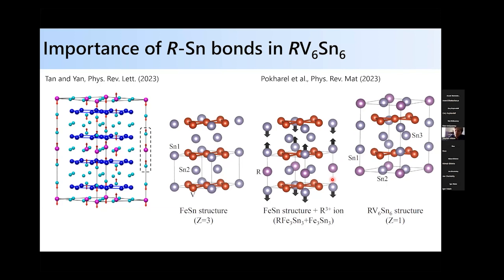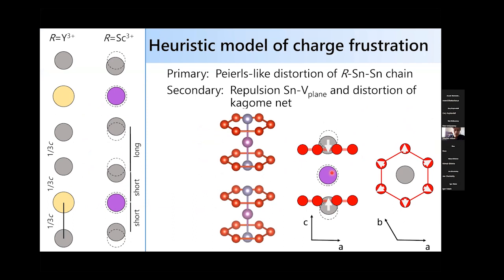So really, the defining trait of how you squeeze these in are these chains and this motion of these tin atoms relative to the rare earth sites. Okay. So then one can imagine what happens. When you think about the structure of the yttrium vanadium six tin six system and you look along these c-axis chains, these tin atoms are being displaced out of the kagome net, right? These chains thread through the centers of the hexagons in the kagome lattice, okay? And in the yttrium vanadium six tin six system, the spacing along the c-axis between these ions is about a third of a lattice constant along the c-axis, okay?